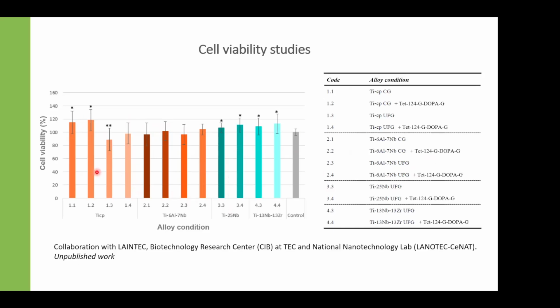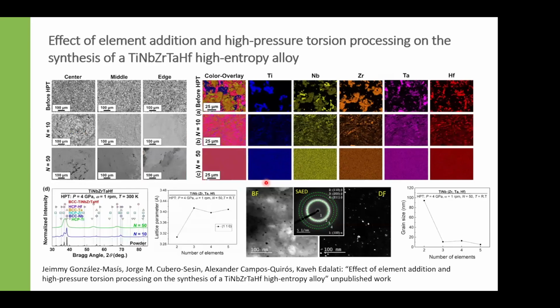And what we wanted to show here also is that the powder consolidated, we did titanium 25 atomic percent, as I said, and also we tried the niobium zirconium alloy. And they are actually equivalent or better than conventional high strength titanium alloys for implants and commercial purity titanium as well. So we can also apply functional surfaces, biofunctional coatings to these materials, and it's a kind of a promising application that we are looking into for manufacturing at least small medical devices and prototypes from these kind of materials.